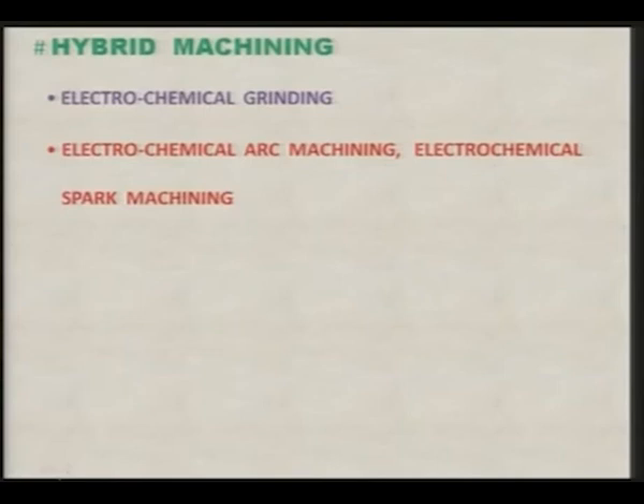Then you have electrochemical arc machining. This particular process is another hybrid process where ECM and EDM both are combined together to take the advantage of the ECM process as well as the EDM process, because ECM has very high material removal rate while EDM has very low material removal rate. EDM creates a problem of surface integrity, especially micro cracks, while ECM does not do so. So, by combining these two processes, the unique feature of electrochemical arc machining is that material removal rate goes much higher than ECM or EDM, and it becomes the combination of the ECM as well as the EDM process.